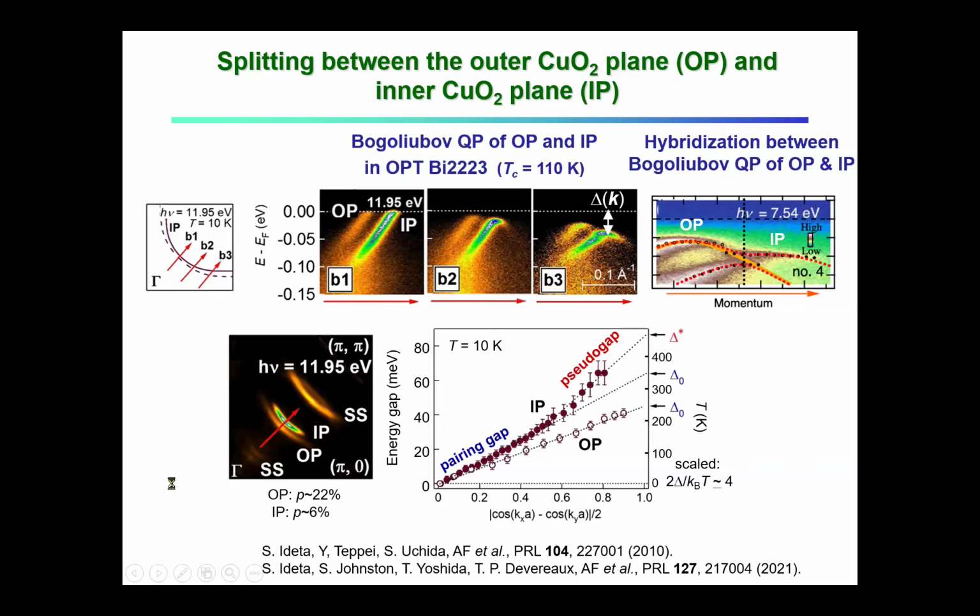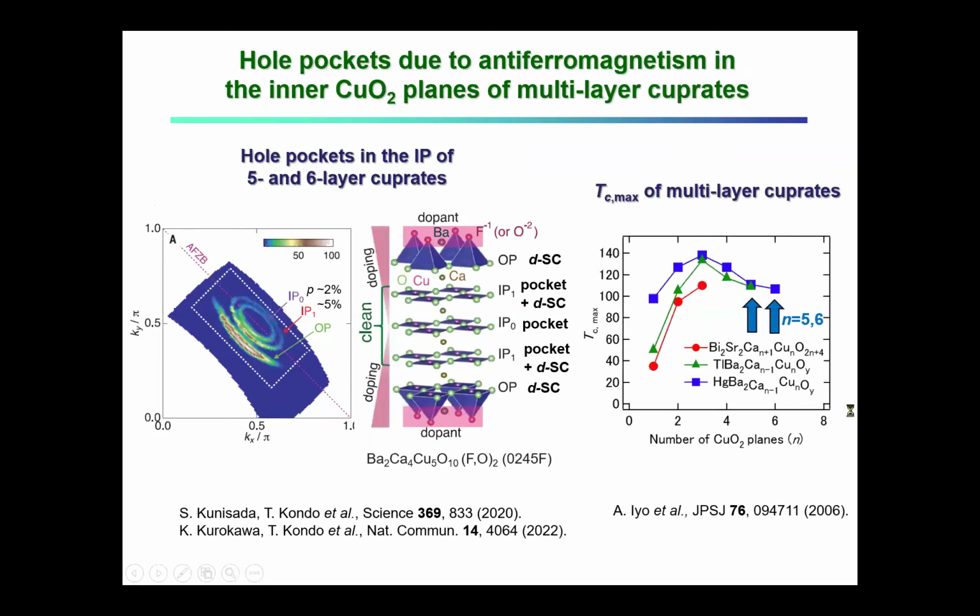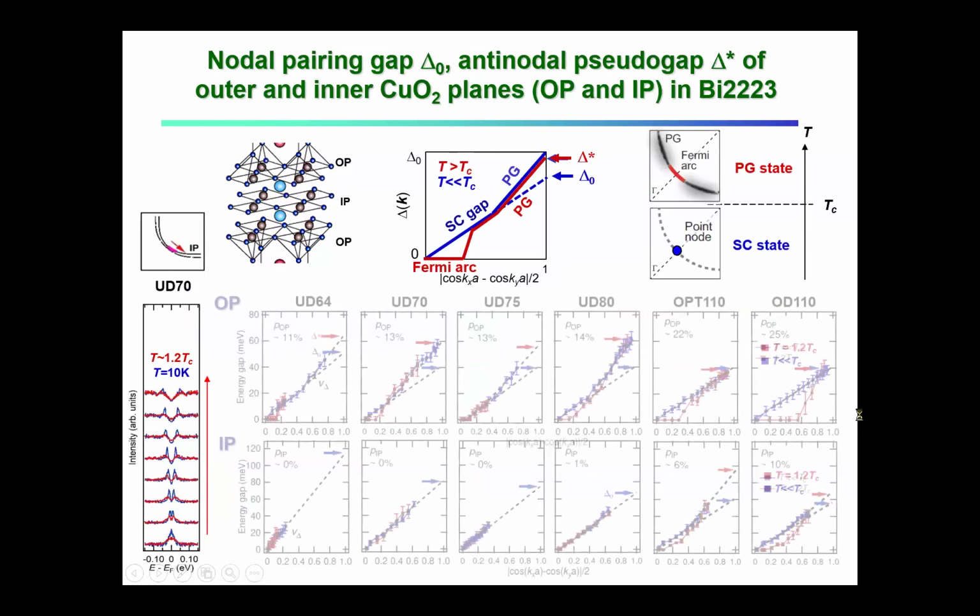Yeah, go ahead. If I could add, certainly the on-site energies are different between the inner layer and the outer layer because of a different coordination. So if you look at the relative ratio of on-site energies and hopping parameters, what you may expect is that the inner layer remains a pure state, while the other two are bonding, anti-bonding split. And as you go close to the zone boundary, you see that splitting. And indeed, that's actually what you find.